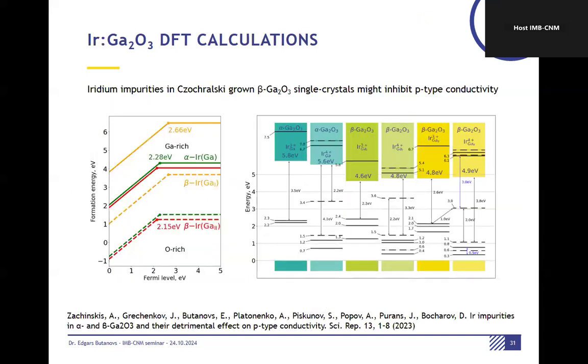What we recently did also, we did some experimental work. It did not match the theory very well, though partly some Raman spectroscopy did, but it's hard to do the experiment correctly. So we put some iridium inside. If you grow monocrystal, single crystal gallium oxide in an iridium crucible, there might be some contamination of iridium in the film. It's mainly in Czochralski growth.